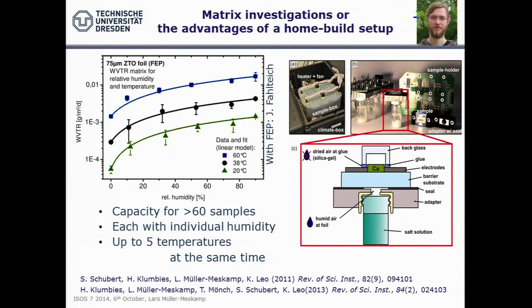Let's have a look at our setup. This is what we are doing. We built a huge homemade setup. So we put the calcium test up here, and then the barrier is here. This is our substrate, and then we have a saturated salt solution below, which gives us a specified humidity, and we put them in groups into larger assemblies to give us certain temperature. This is maybe not as precise as you want to have it in a certified measurement, but it's good enough to give you a number, to give relative comparisons.